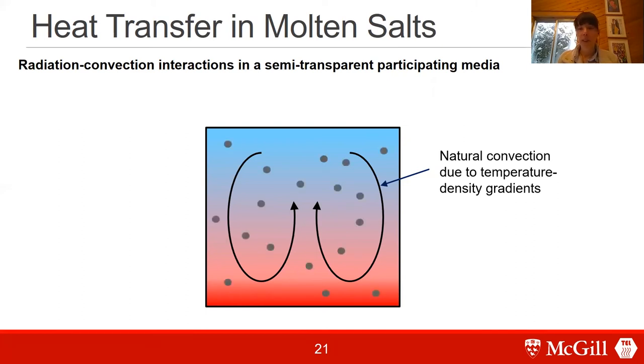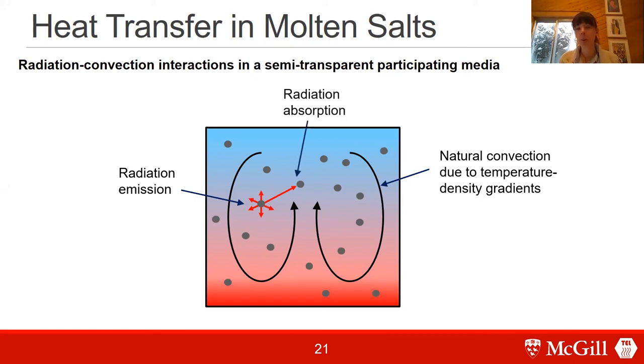So in addition to the natural convection, every point inside the molten salt, these aren't actual particles, they're just points inside the molten salt, can emit thermal radiation, and this thermal radiation is going to be quite intense because we're dealing with very high temperatures, 700 degrees Celsius and so on. Because it's semi-transparent, this radiation can travel within the bulk of the molten salt and get reabsorbed or scattered somewhere else in the molten salt. So we end up with this interaction between radiation and convection that's very difficult to predict.